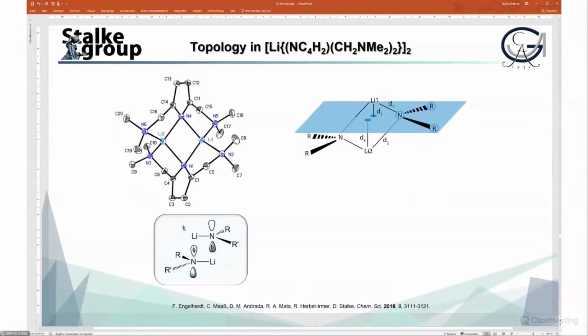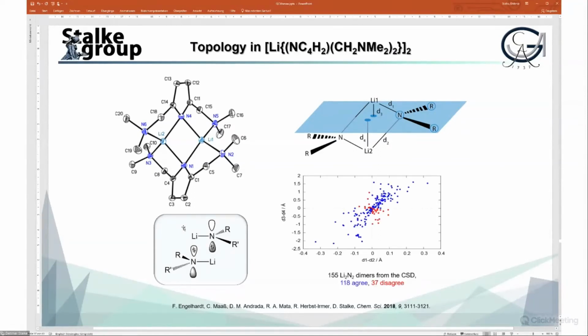And then we looked at the database for all the lithium amides and all the lithium amide bonds in there, which would, of course, mean that the relation between D3, the distance of one lithium from the plane of one amide, and the distance of the other one, that needs to be, say, maximum.